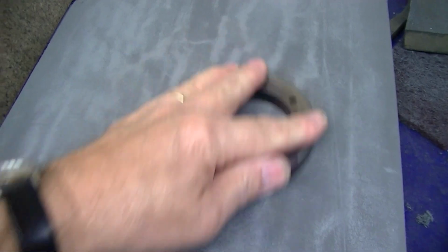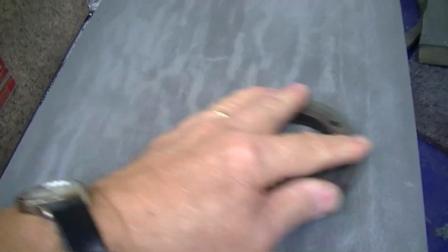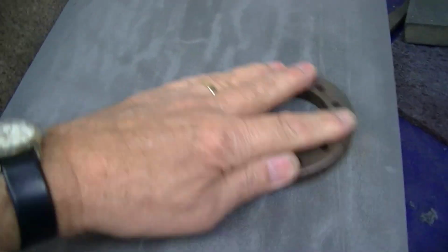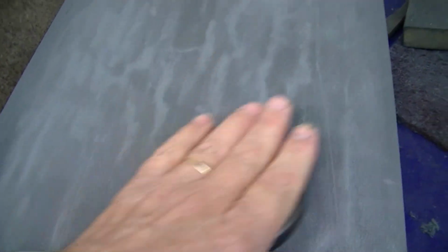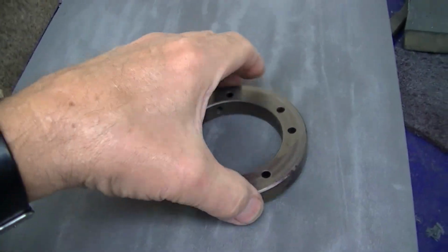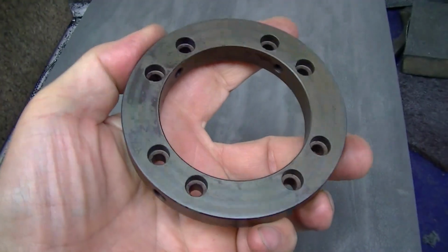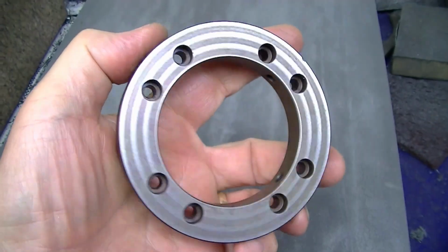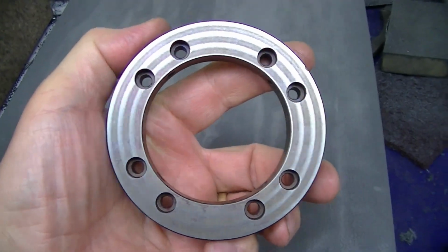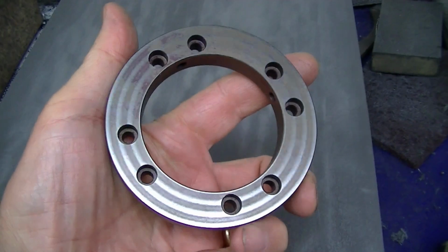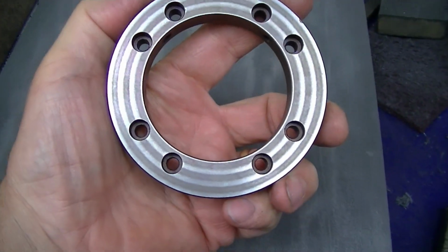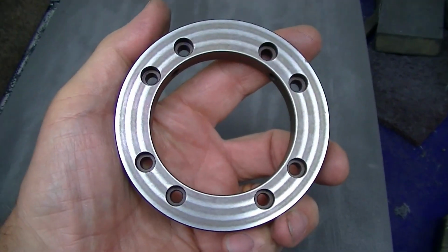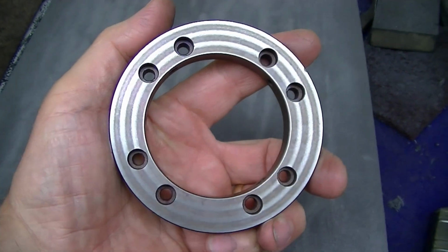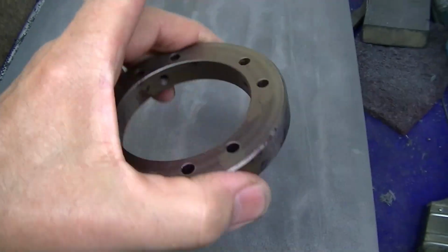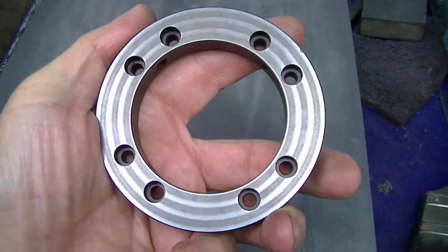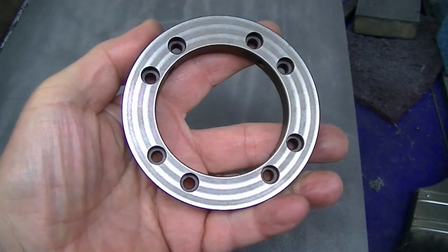This is a perfect example of the use of the magic sanding plate to make sure that the surface you're sitting on is basically flat enough that it will not warp when it touches down on the grinder and the chuck pulls it down tightly. So this is flat enough that you can put this on as is, not have to worry about it being out of shape and warped enough that when you release it from the chuck it springs up and gives you a different size. So it saves an immense amount of time, and lets you see what's going on.